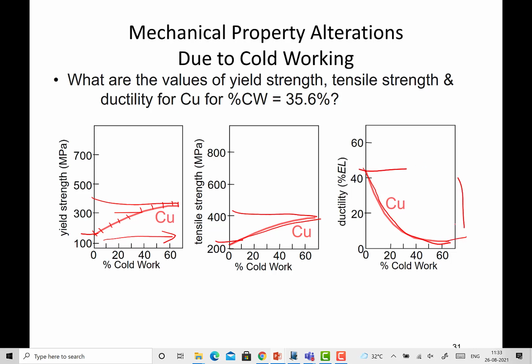Different metals respond differently to these kinds of changes. So that is what you can learn from these curves, the way by which the two metals will be responding, A and B. In this case, the work hardening is very limited beyond the yield point, and in another case the work hardening is significant. So two metals respond differently to the cold working and the deformation. So depending upon the metal which is being subjected to the solid state joining, experiencing the deformation, the kind of change that will be taking place in the yield strength, tensile strength, and ductility may change significantly depending upon its work hardening capability.